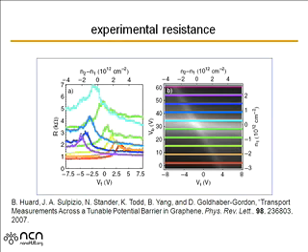It goes up very high at that point where our conductance went very low, and then it turns around and comes down. Again, qualitatively, it looks similar. But there's one very important thing: if you look on the side where you have a PP junction, or if you look on the side where you have an NP junction, and on the side where you have an NN junction, you'll see that they're not symmetrical. You get a lower resistance. Whoops, I guess this is the NN side. You get a lower resistance when both sides are N-type than you do when there's a PN junction. That's the experimentally observed asymmetry between PN and NP junctions.